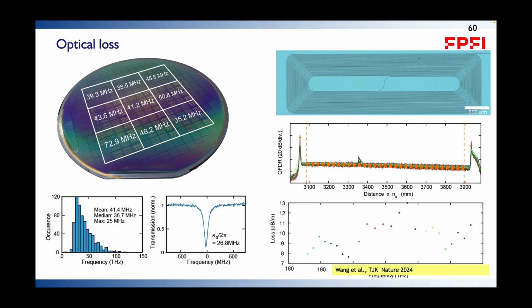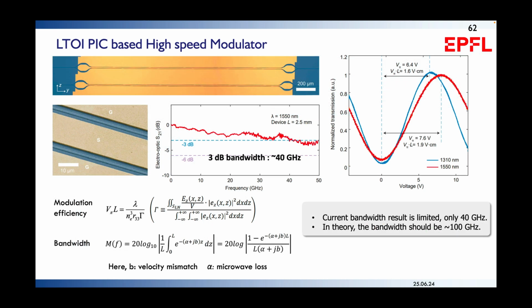You see a spiral here that has a path length of 3,900 millimeters, so it's a long spiral, very compactly wound due to the tight confinement. And you also see here microresonators with quality factors actually close to 10 million in this material platform. So what can you make with this?